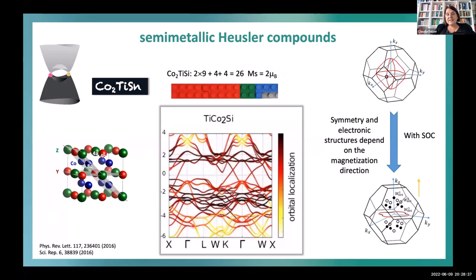And as I said, in magnetic compounds, simply by definition, all these crossing points in the band structure, these crossing points you see here, my red pointer, you know, these crossing points are Weyl points. So there's an inflation. But here it's very nice because they are in the gap of one spin direction. So you really have very nicely pronounced crossing points. But the disadvantage is that here is the Fermi energy, the zero energy. Up to there, the electrons are filled. So it's more or less in the unoccupied states. So we saw a nice prediction, but it doesn't make sense.